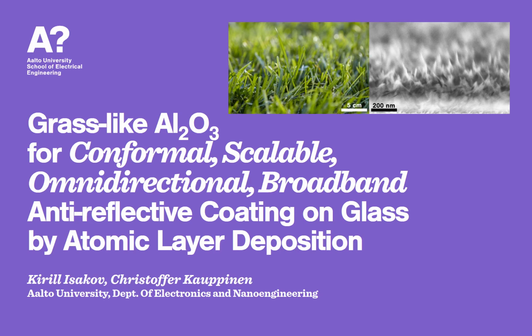My colleague, Christopher Kaupinen, and I have developed a process to transform atomically layer-deposited aluminum oxide into a nanoporous state. We have called this film Grass-like Alumina for its structural resemblance to grass, as you can see in the photo here. Grass-like alumina performs as an excellent anti-reflective coating, enabling high omnidirectional and broadband transmittance. Its fabrication process is easily scalable and allows conformal coating of complex structures.